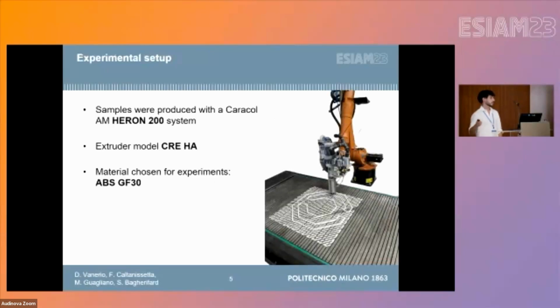From this, we pass to the instrumental setup. The setup is, as I said, a robotic arm with an extruder at the end. And as a material for the experiment, we chose ABS with 30% glass fiber, because it is a commodity material we use very often for many applications.